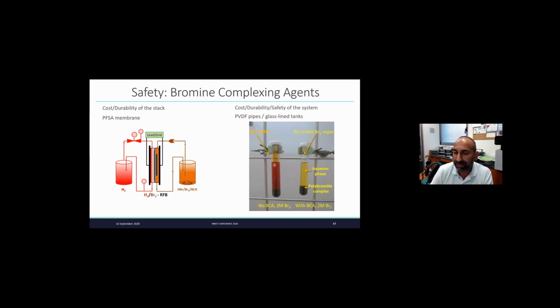So when you have that, here you can see without using complexes, you have a lot of vapor pressure of the bromine, even if you're working with 2 molar, which is not the highest concentration, and at room temperature. But if you're using some complexes, then you don't have any bromine vapor pressure, and it's safer, and then you don't have to invest in very expensive pipes and tanks and everything. So that's something that we work on.